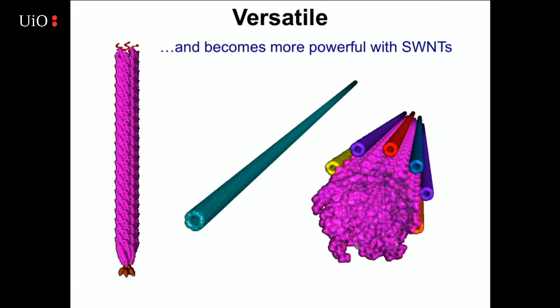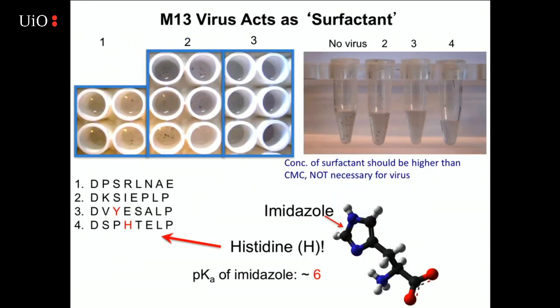And so in order to do this, my students took M13 bacteriophage, and they engineered the carbon nanotubes to sit in all these pockets along the outer surface of this material. And it ends up that the virus actually acts as a surfactant to be able to keep these nice and stable in solution and still have spaces to grow other materials like titanium. So they started with a library of M13 bacteriophage, and they looked for ones that could keep carbon nanotubes in solution to act as a surfactant.